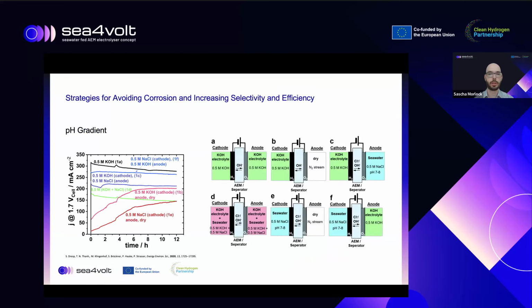There are different strategies to avoid corrosion after all, and also to increase the selectivity and efficiency. There was a study that compared different ways of feeding electrolyte, KOH, seawater, and a mixture of KOH and seawater into a cell. As you can see here, figure A is the conventional setup, which is more or less the AEM approach. That also has the highest current at a cell voltage of 1.7 volt, as you can see here on the left-hand side. However, this blue curve, which is F, means we have a pure seawater feed at the cathode and a pure KOH feed at the anode. It has a similar performance to the setup, and it's also very stable. So by using this asymmetric feed, it's likely that you can have a good performing system, but also a stable system. And this is also what we're doing in sea4volt.